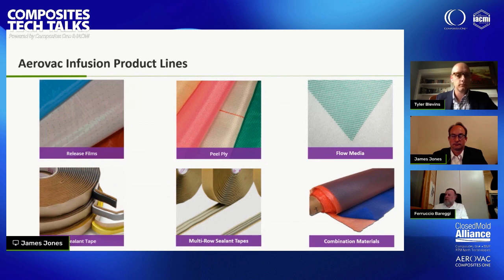So James, if you want to, okay. So another material that we have involved in the manufacturing of blades is peel ply. As James was mentioning before, peel ply is a porous, generally polyamide textile that is placed over the part underneath the infusion mesh, and it is used for peeling it off at the end of the process, as the name says. You generate a very clean and homogeneously rough surface ready for secondary bonding operation.